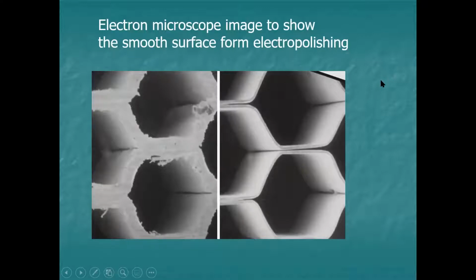If you were to look under an electron microscope at high magnification at an object which has been electropolished, with the before surface on the left-hand side and the after surface on the right-hand side, you can see it's the same object, but it's been changed significantly. First of all, it's not as thick. The wall thickness here is clearly thicker than the corresponding wall thickness here, which is much thinner. And also, this is a rough surface, especially on the inside of the object. It's like a honeycomb, in fact. But the surface finish of the object after it's been electropolished is smooth.